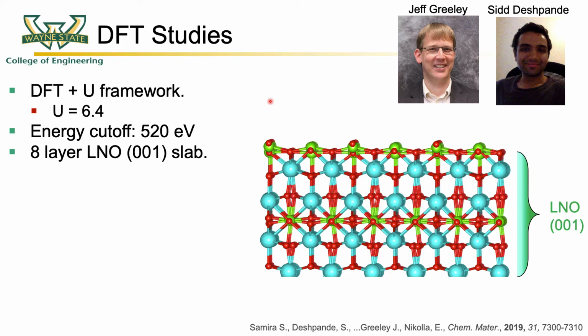Although experimental studies are valuable in determining the distribution of the discharged products, they are limited in identifying this near-surface interface between the formed lithium oxygen species and the surface of the catalyst. In order to understand this interface, we turn our attention to atomistic simulations using DFT studies in collaboration with Professor Jeff Greeley's group at Purdue University.